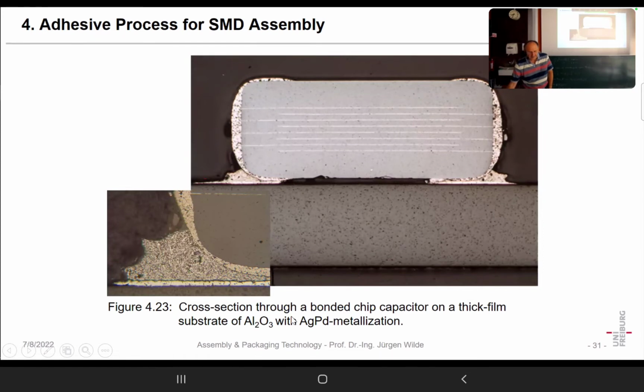Again, here is that example from a surface mount device. What is not so beautiful here is that there is no more glue under the chip here. That was a different chip. Here we have a little more under the chip. With respect to shear strength and with respect to fatigue behavior, it is better to have a certain amount of adhesive under the device, but that also depends maybe on the size of the chip. And in a pick and place machine, you have only a limited possibility to control the pressure you use for putting on the chip.